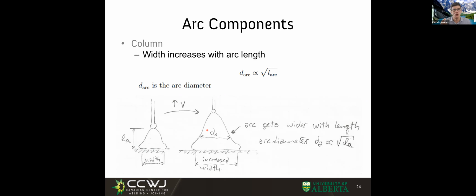And this is good to know, because if we have a bead that is too narrow and we want to make the bead wider, one of the things we can do is increase the voltage such that the arc length is longer, and then the diameter of the arc is going to be broader, right? And now we can even anticipate by how much we should do that.